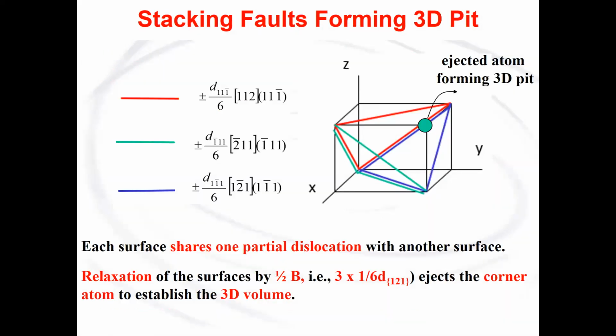And if we were to look at this in a unit cell, we can see the 3 stacking fault surfaces here. So the red one is plus or minus a/6 112 on the 111̄ plane. The green one here, there's another surface in here. It's a/6 2̄11 on a 1̄11 plane. And then the third one here is a/6 11̄2 on the 11̄1 plane, and that's here. And so we have these 3 surfaces which are intersecting at this point in here.